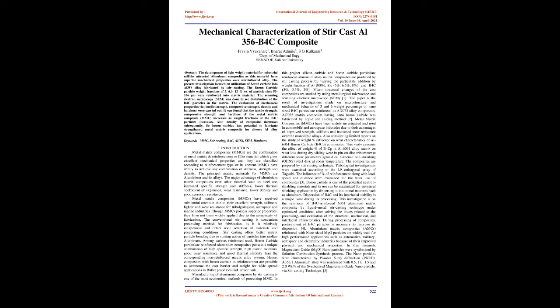It was found that the tensile strength, compressive strength, and hardness of the metal matrix composite, MMC, increase as the weight fractions of the B4C particles increase. Also, the density of the composite decreases subsequently. So boron carbide has the potential to fabricate strengthened metal matrix composite for diverse alloy applications. Keywords: MMC, stir casting, B4C, Al356, SEM, hardness.